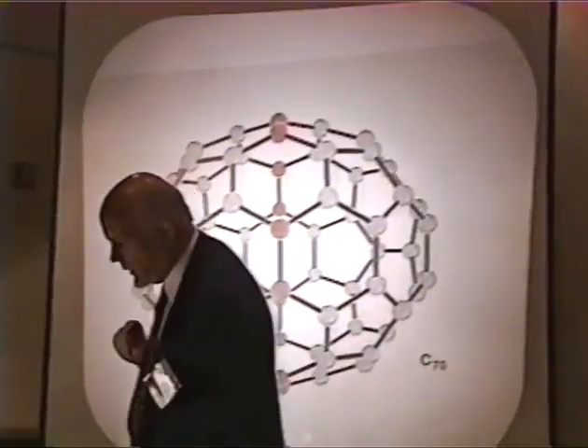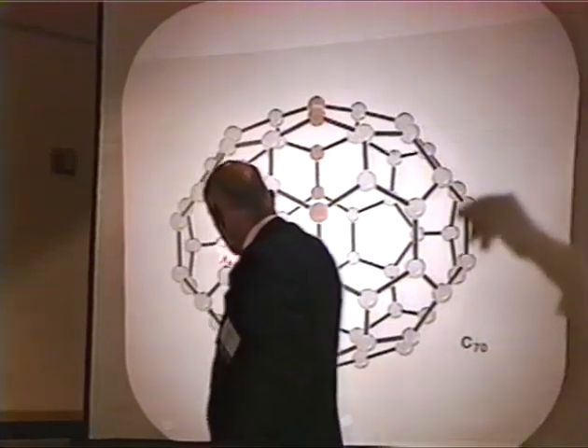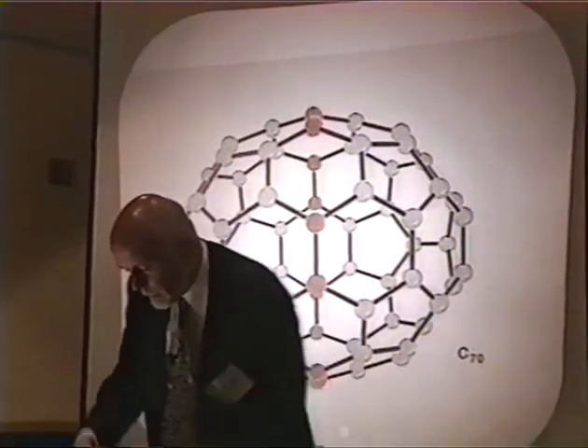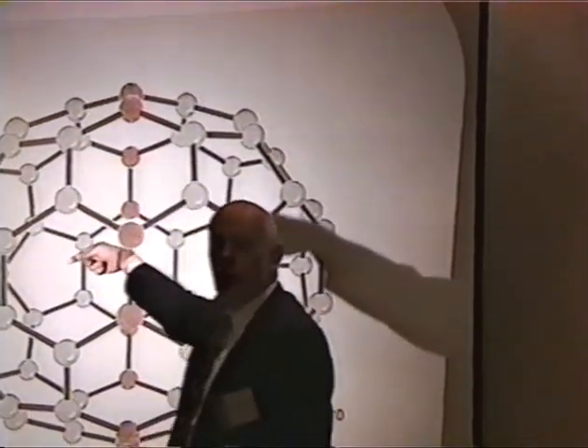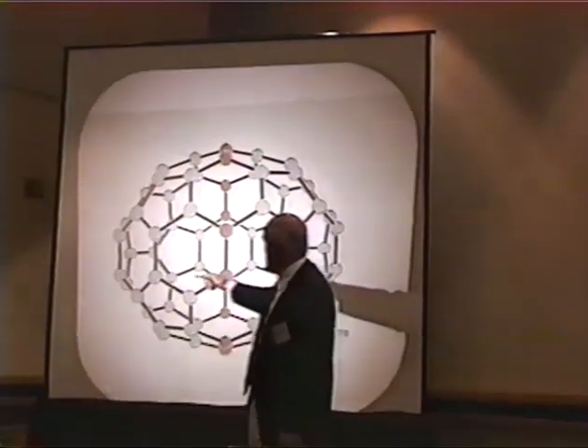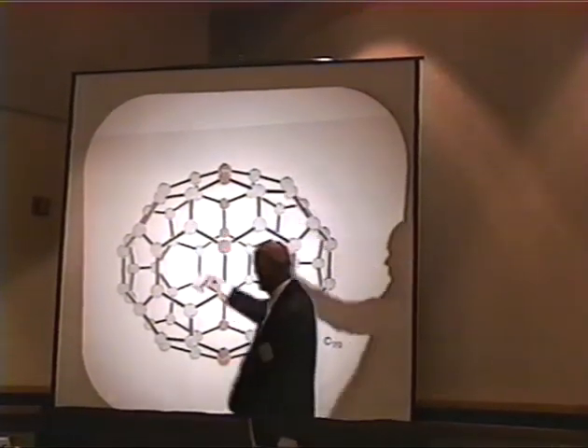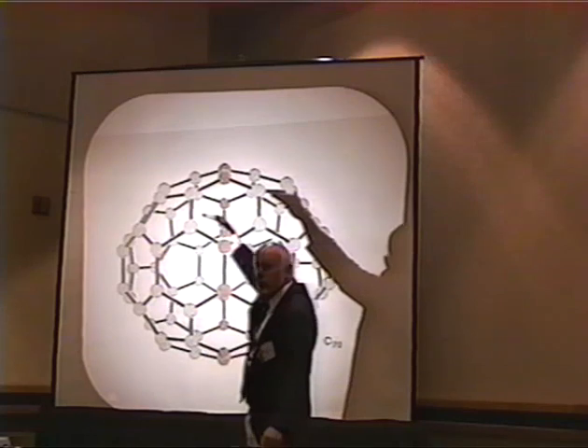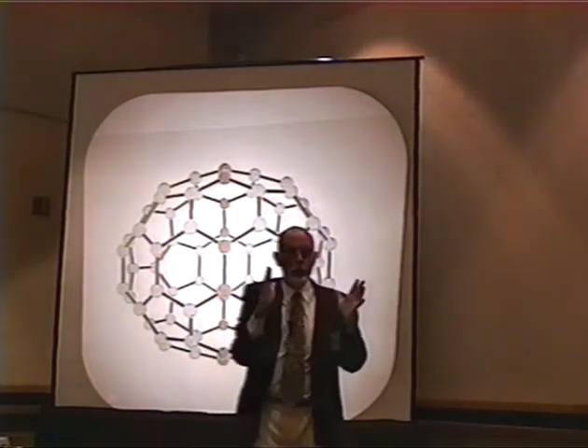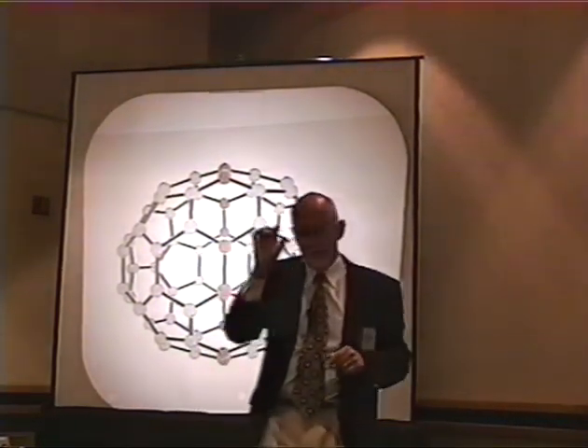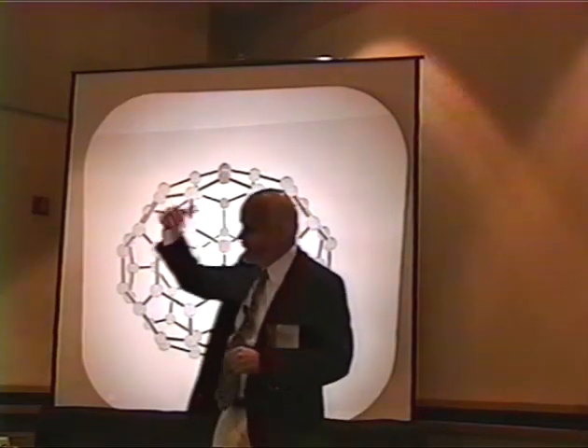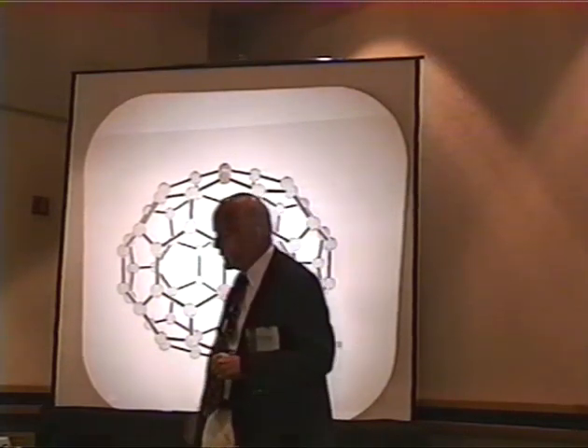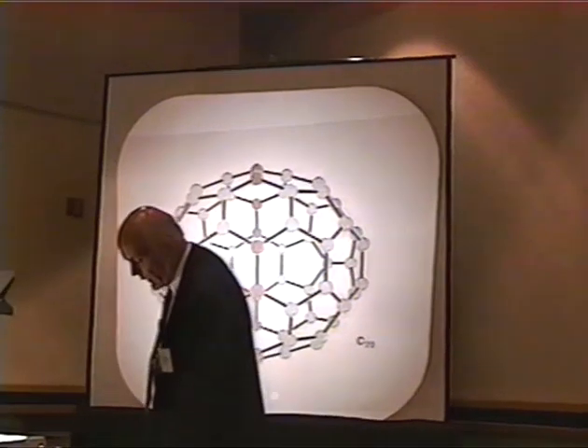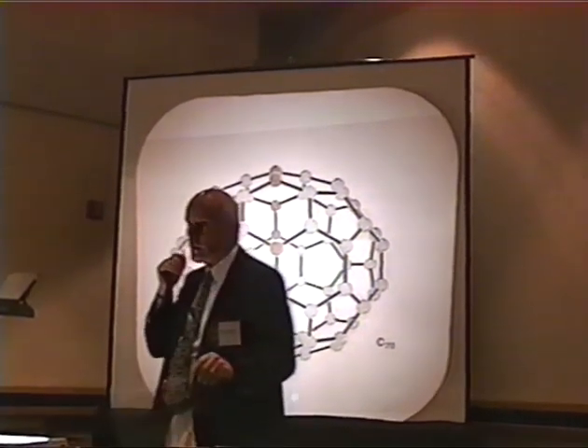Now, it turns out that that tube of this diameter is pretty highly stressed. If you take the graphene sheet and you wrap it around this diameter cylinder, which is 7/10 of a nanometer diameter of the cylinder that has the nuclei, or almost precisely 1 nanometer diameter at the van der Waals distance on that side, the energy to stress the graphene sheet around that cylinder is rather significant, and it is not the one that nature likes to make the best.